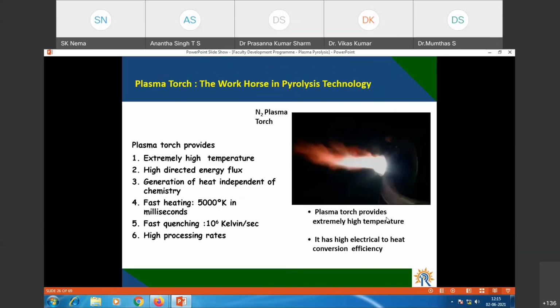This is another plasma torch which we have developed. It is a nitrogen based plasma torch, where the nitrogen is flowing between the electrodes, and this plume is coming out, and this torch is the workhorse. This is the very important device, torch and power supply, which is giving you very high temperature. In the absence of oxygen, you can generate high temperature, and you can see the many advantages.